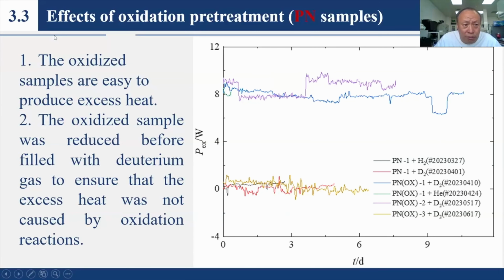Another most important result is the effect of oxidation. This is 6 runs of experiment. The first time we used hydrogen gas, the black curve. We can find there is no prominent excess heat. The second time with deuterium, the red curve, we can find there is no excess heat. The third time is the blue curve. We can find there is prominent excess heat. It is 8 watts. This is the oxidation pre-treatment sample.